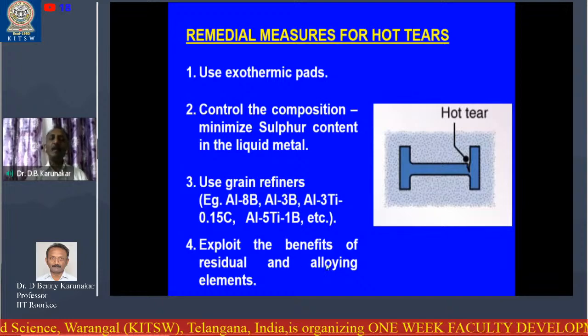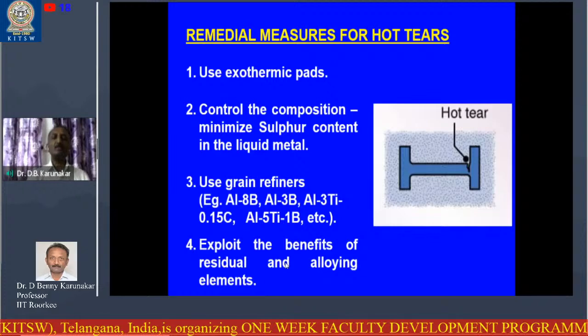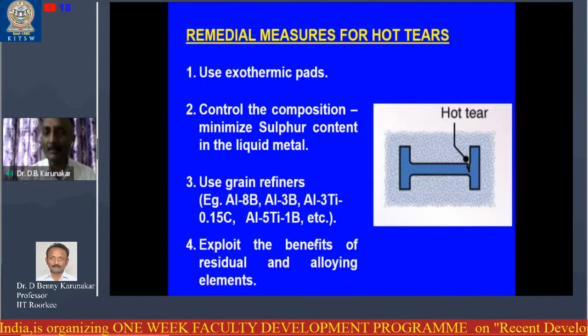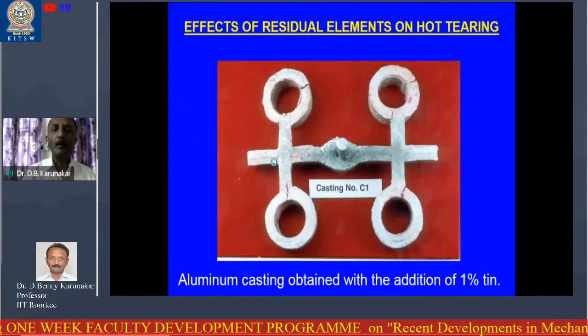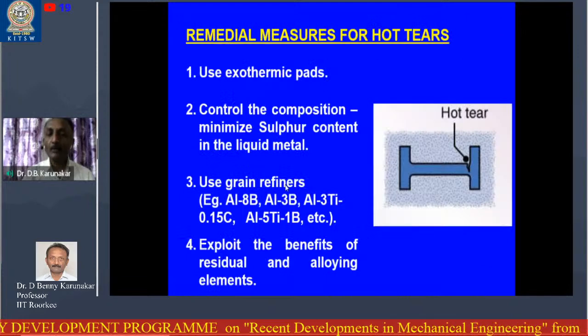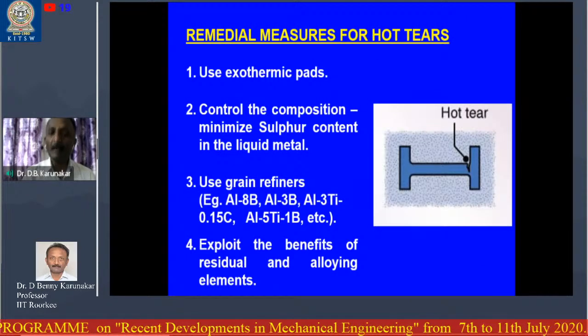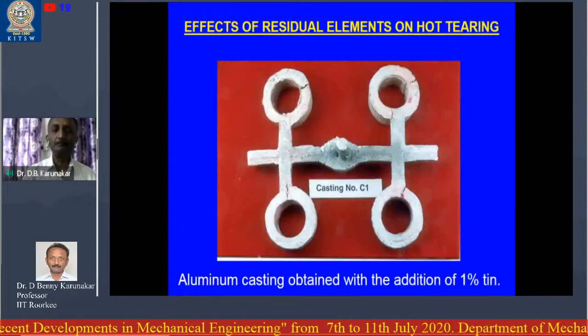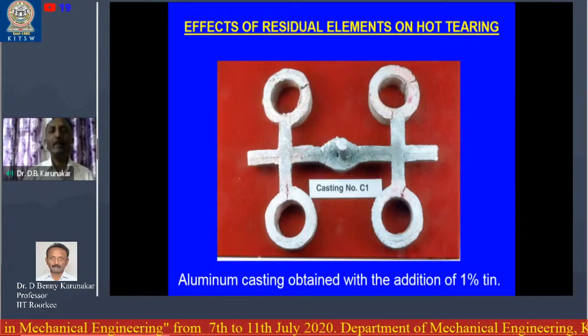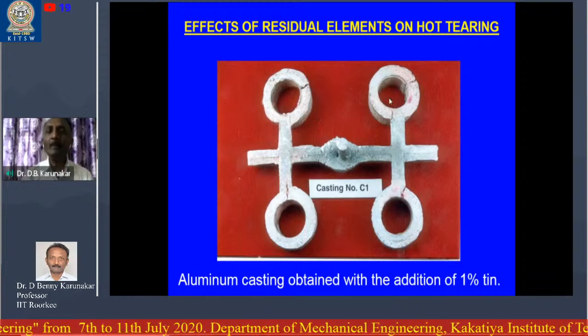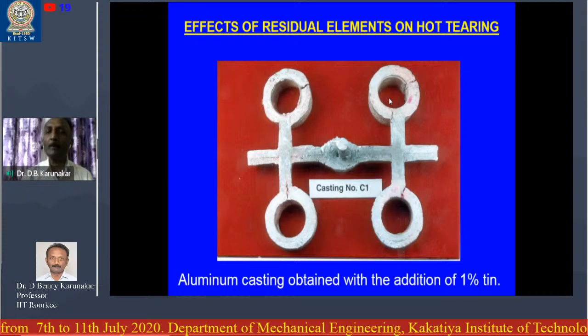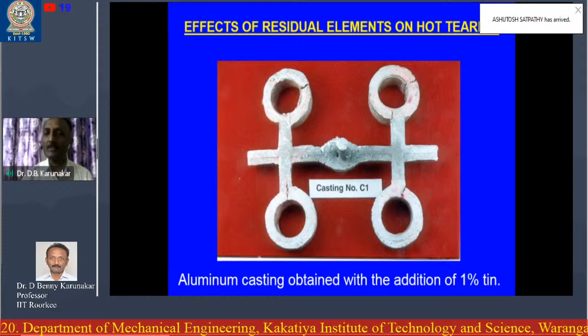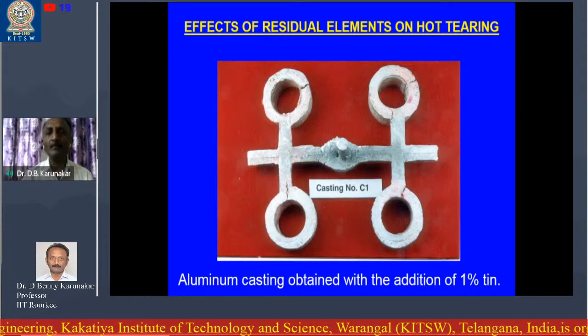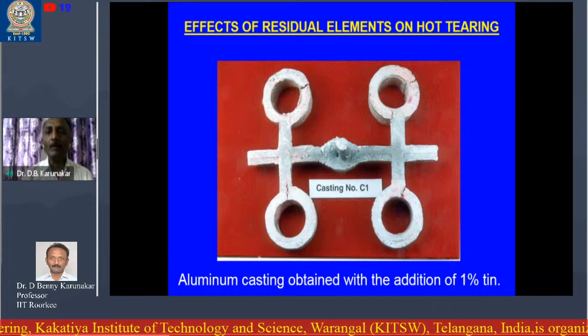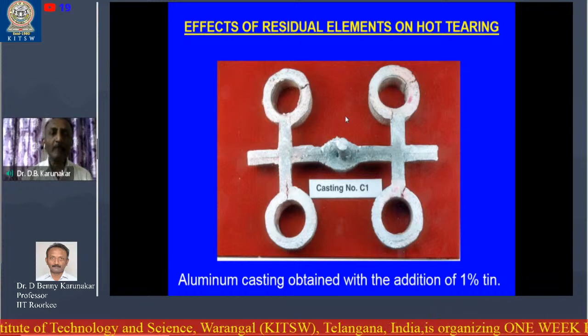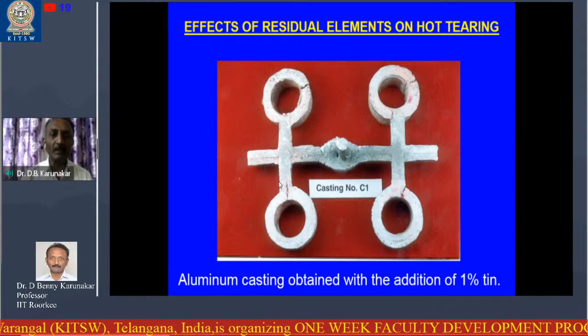Next, exploit the benefit of residual and alloying elements. We have actually worked on this, to see how to exploit the benefit of residual and alloying elements. For example, we conducted experiments with aluminum and 1% tin, again a very small proportion. When we added 1% tin, there were prominent cracks. You can see here, these are the cracks.